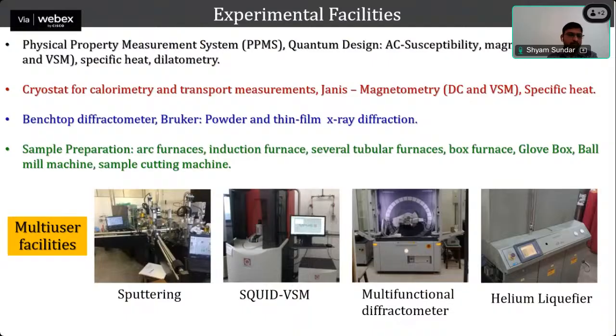We have multi-user facilities at our institute, where one can prepare thin films using sputtering techniques, and the SQUID VSM, which is a multi-user facility that works up to 7 Tesla, down to 1.8 Kelvin. We have the multifunctional diffractometer, where you can even measure X-ray diffraction as a function of temperature, from 12 Kelvin up to 300 Kelvin, and it can measure thin film samples as well. And then we also have our own helium liquefier to get the liquid helium.